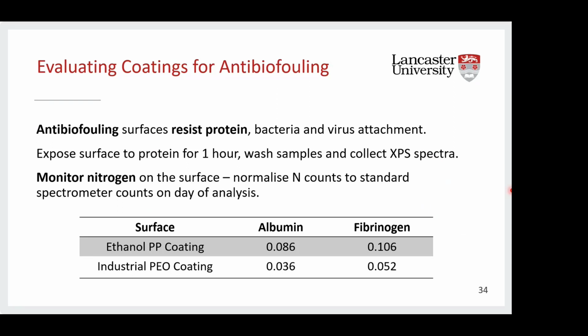Alongside our production of coatings, we've been looking at methods to evaluate anti-biofouling coatings. When I say anti-biofouling, I mean surfaces that are able to resist proteins, bacteria, and virus. Before you consider directly exposing coatings to bacteria, it's a good idea to look at some of the key proteins employed by cells and bacteria to determine whether the surfaces are even viable as non-fouling. So we selected albumin and fibrinogen because they're already known to be vital for bacterial surface attachment. These two proteins are actually observed in that conditioning layer that's priming surfaces for bacterial attachment that we saw right at the beginning of the biofilm development cycle.